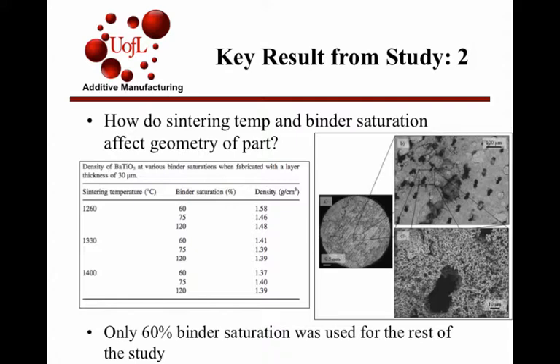This diagram here is some SEM photos. It illustrates, more zoomed in, that as the binder forms the part and then as it is sintered, the binder evaporates or dissipates and leaves these holes behind, and that's what causes your low densities if you have a lot of binder saturation in the mix.